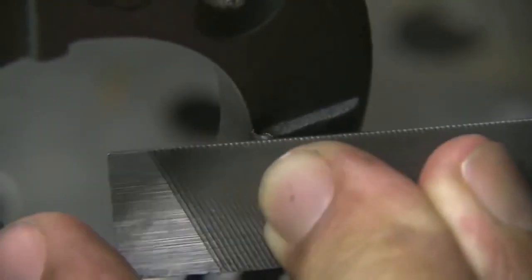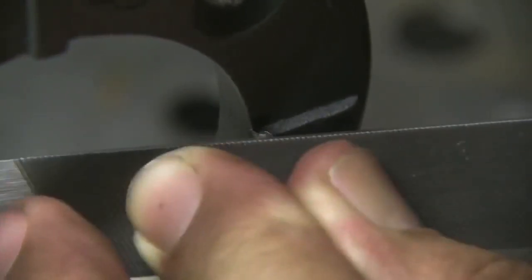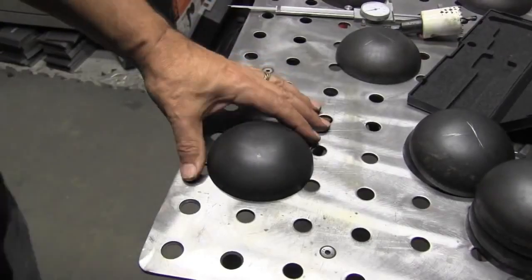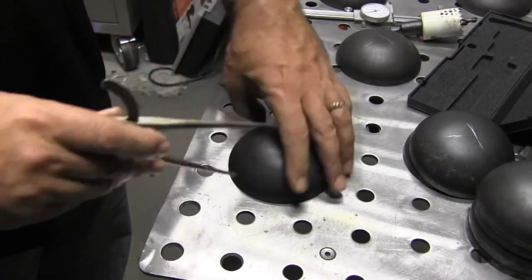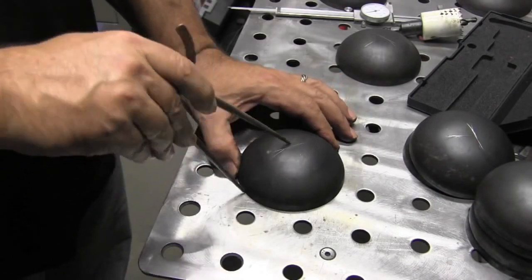Not all metals will do this you can do this on mild steel and you can still file that but if something's got a lot of carbon content like cast iron does that'll give you a heads up on if you're gonna have trouble welding it or not so reason I bring that up is because I'm going to do the same little test on a little threaded fitting here in a minute.